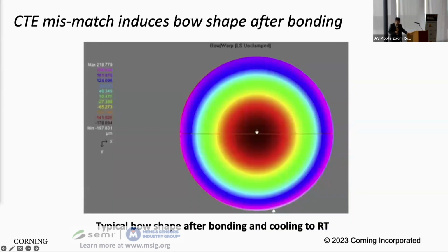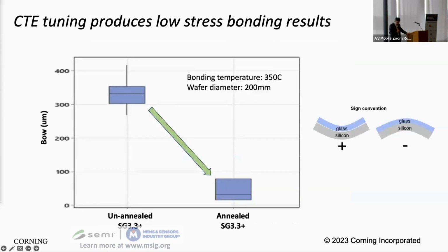So we want to see what happens if you bond this to silicon at these two different conditions. And typically when you have stress, it's symmetric. So the bow shape is very nice looking, as I show here. And then the magnitude of the bow, if the CTE is mismatched, you have 300 microns. This is a 200 millimeter diameter wafer. We have 300 micron bow. But if you anneal the glass and make the CTE match very, very good, it drops to less than 100 microns. So if your device is sensitive to bow, we have the means of changing the glass CTE to make the bow very small.